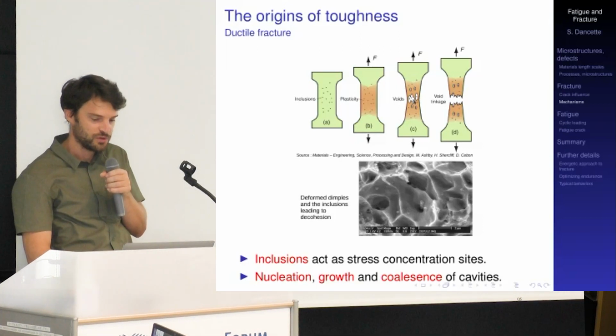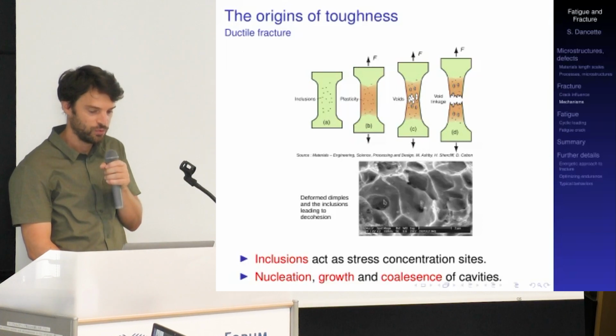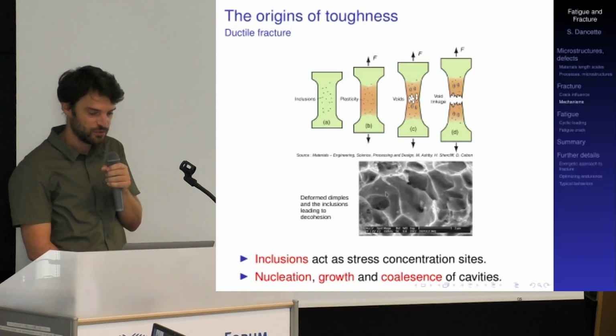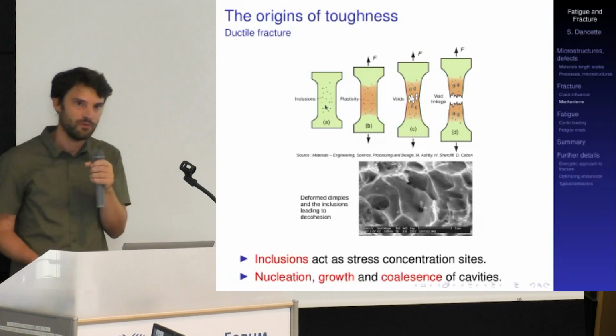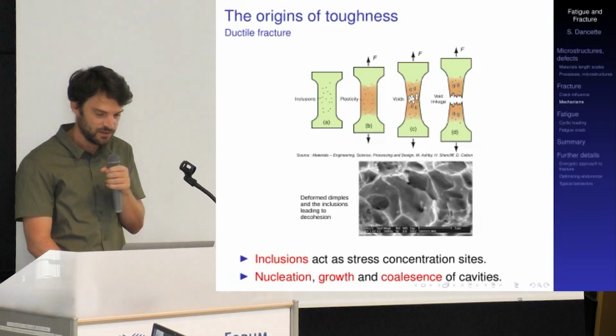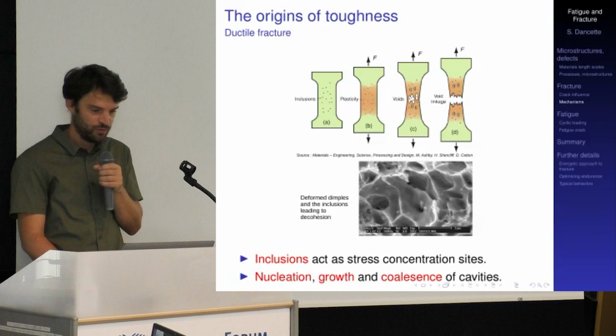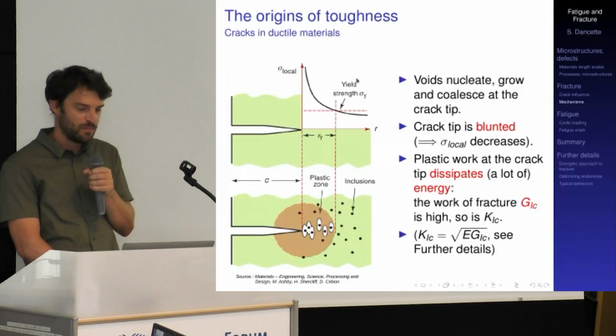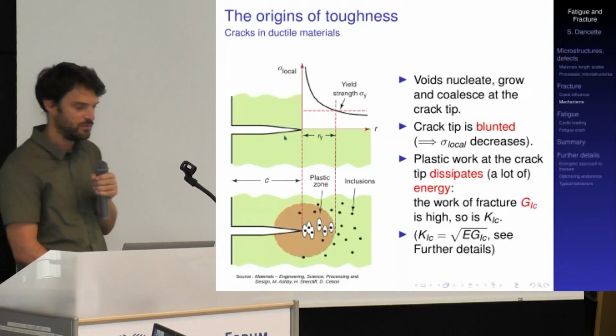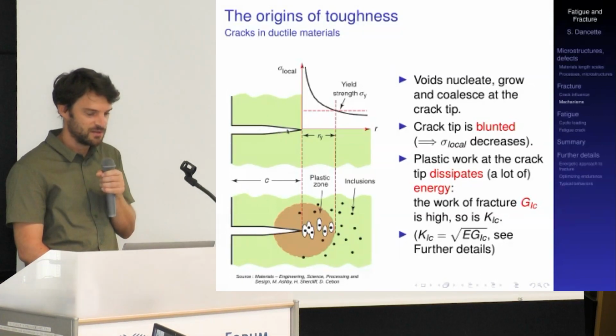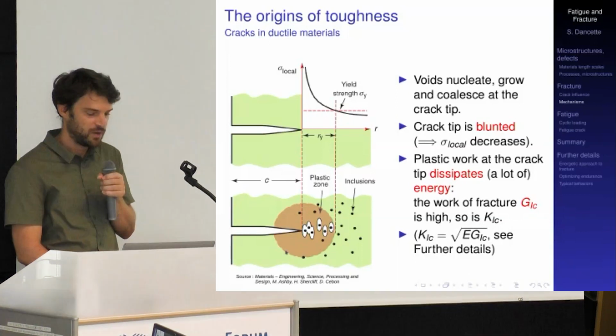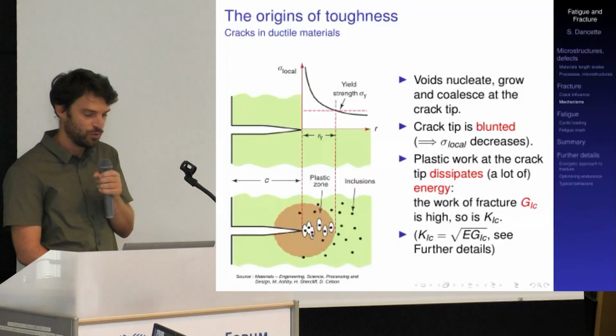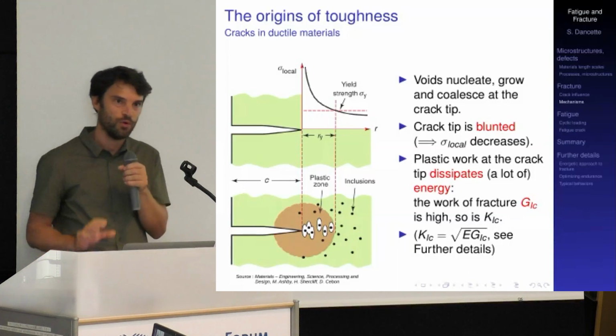If you look from the top on the fracture surface, you see the result of these void growths that coalesce together, and it is also noticeable that you can retrieve some of these inclusions. Here you have the original inclusions that were at the source of the nucleation of the final ductile crack. Okay, so that is ductile fracture. This is also what is happening in a ductile material when you have an initial crack in the part. Because of stress concentration ahead of the crack, the ductile material will tend to develop a plastic zone ahead of the crack tip. Inside this plastic zone, locally, you will have this mechanism of initiation and coalescence of fracture occurring at the crack tip.